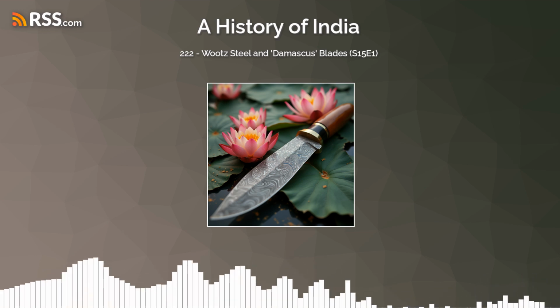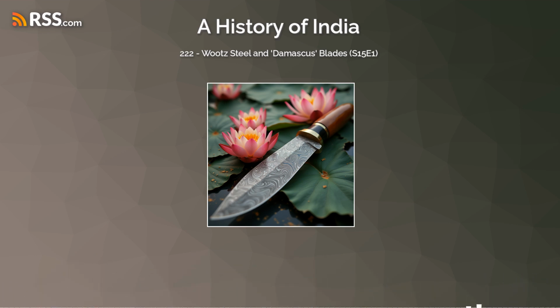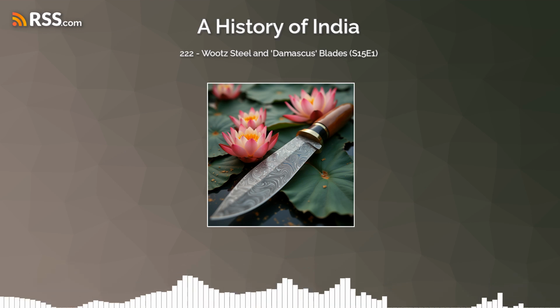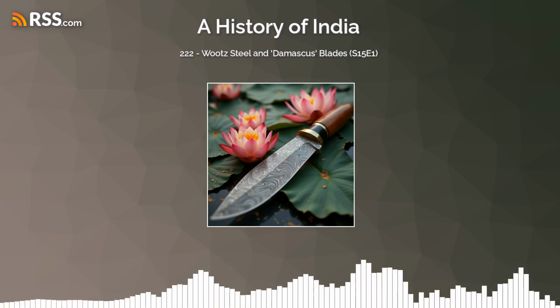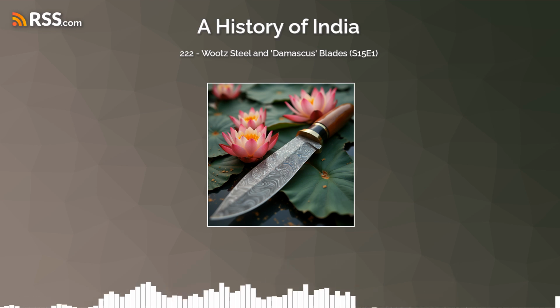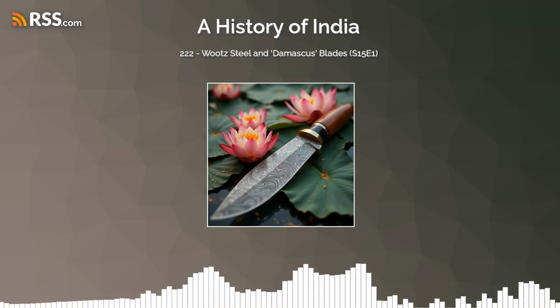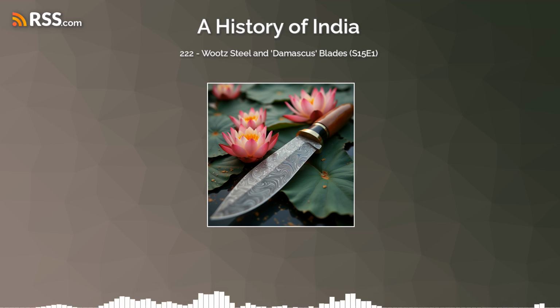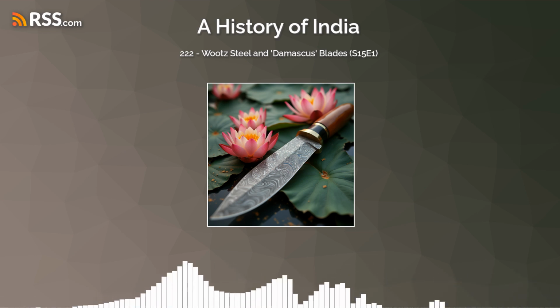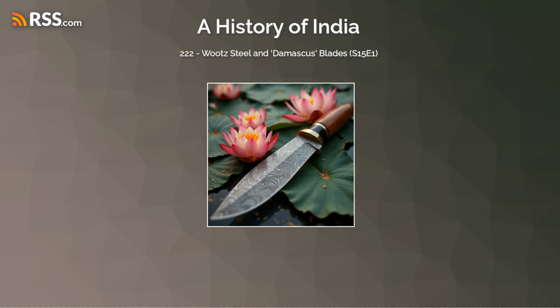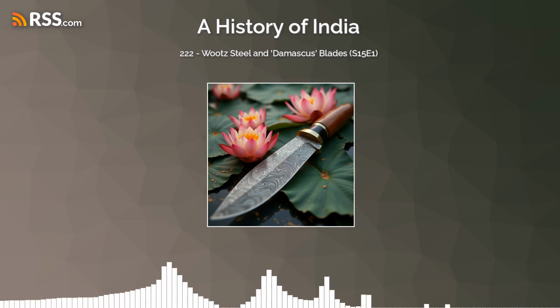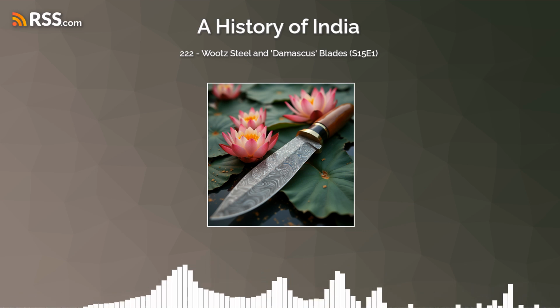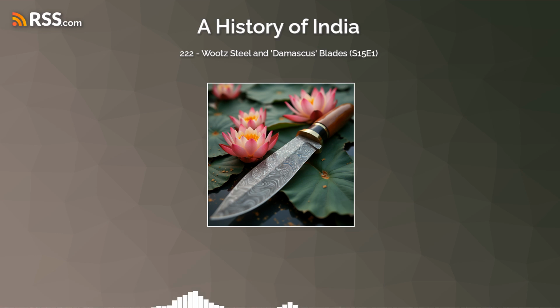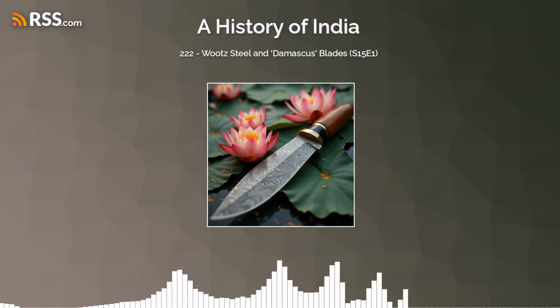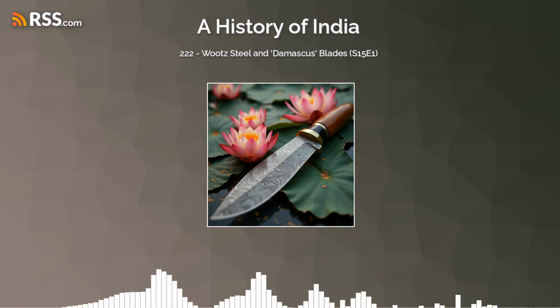So that famous swirling pattern, the firin, as the Arabic sources called it, was already visible on the ingot? The potential for the pattern, the basic structure, was absolutely set during the casting and slow cooling inside that crucible. That dendritic structure, those tree-like crystals of austenite, the high-temperature form of steel growing inwards, that was the foundation. As it cooled further, the high carbon forced cementite to form within and between these dendrites. But the really visible famous pattern, the firin, that only became fully clear after the ingot was skillfully forged into a blade and then etched, usually with some kind of acid.